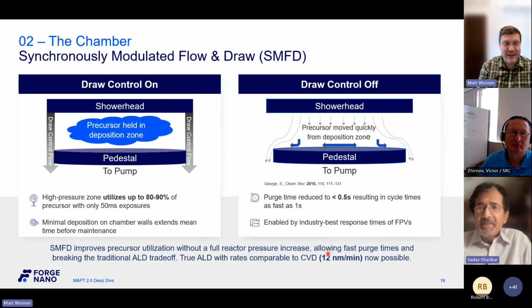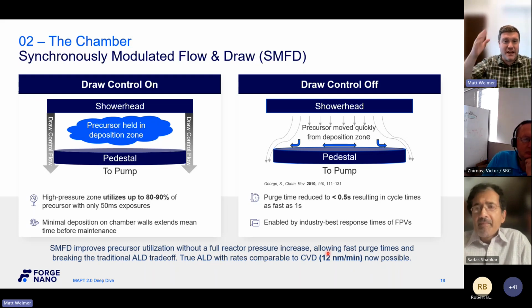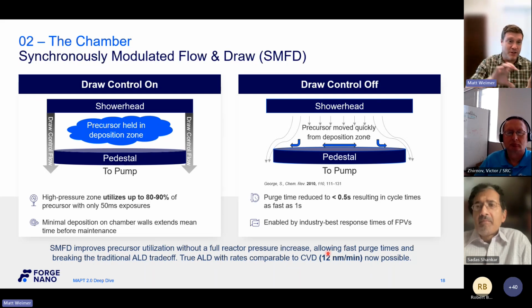So one of the things, if you think about it, I think about it maybe slightly differently. This turbulence is helping us to circulate our precursor over that deposition zone, right? So instead of having these laminar flow lines where the precursor is defined by those flow lines and the diffusion path lengths at the given pressure, this adds turbulence to that entire area. So instead of having localized hotspots dictated by those laminar flow lines, now you have a mixing of the precursor. Not only do you have the laminar state and the turbulent state, you also get the transitions between the two. So you get to move precursor in ways that are quite unique.